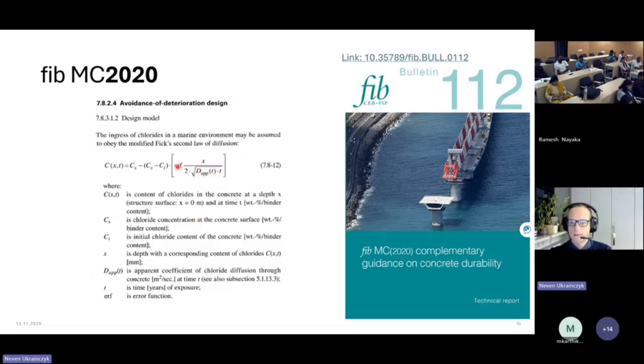We have the error function here, and this apparent diffusion coefficient is also time dependent, because the concrete is hardening. You have the pozzolans which are slowly reacting, so they are improving the microstructure. So this is time dependent, it's mostly believed to be because of the continuous hardening of the concrete, but I would also argue it's because of other effects, like binding effects and pH effects on binding.